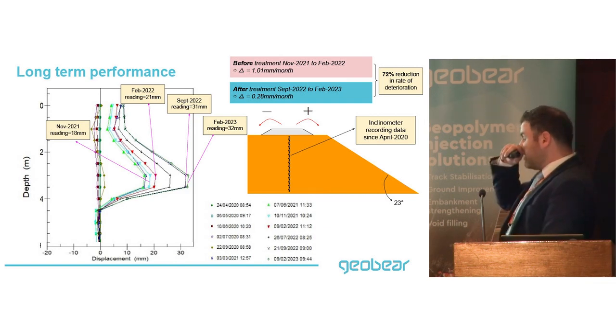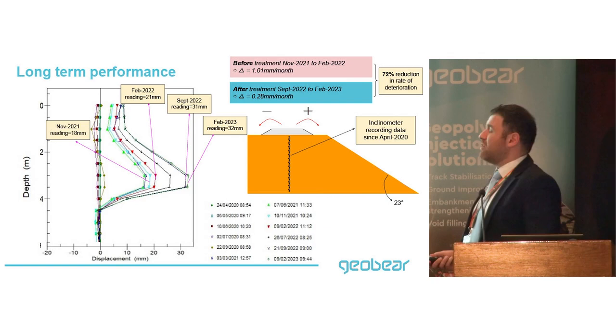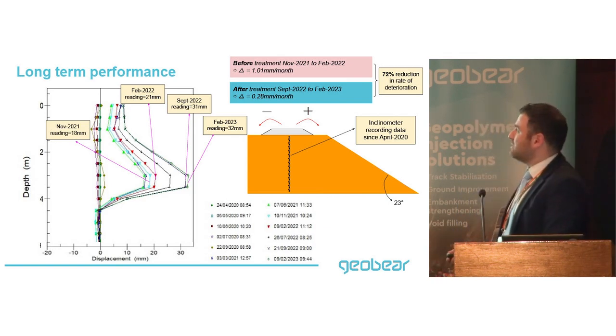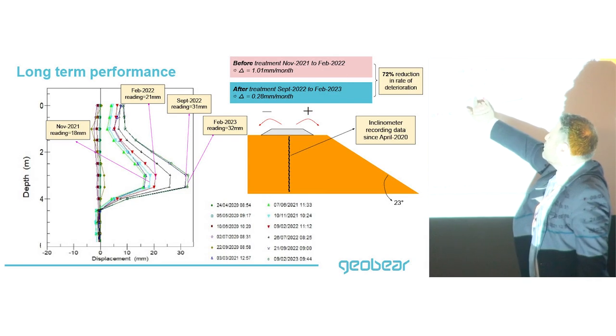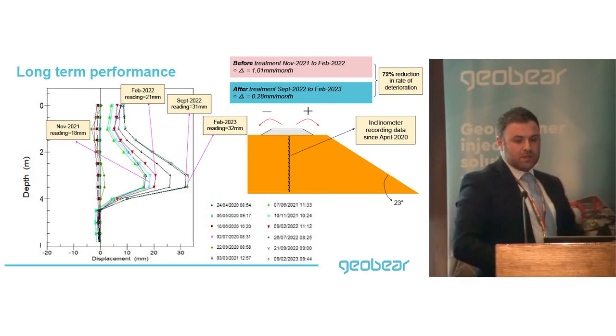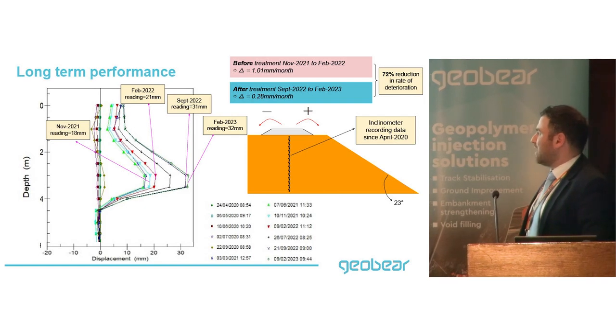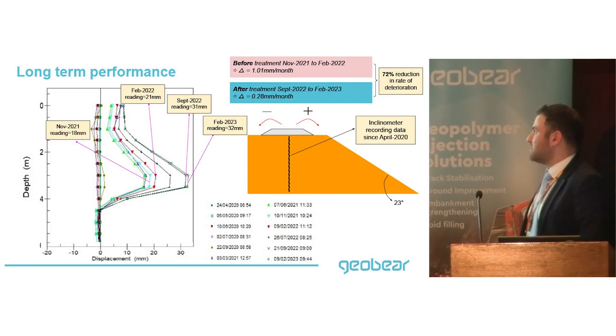That will give you a rate of deterioration of about 1 millimeter a month, roughly, if you take the delta between the two measurements and normalize them by the number of months. This is really quantified by the gap, which shows how much movement has been exhibited between those two periods in terms of how the core of the embankment has actually moved sideways towards the river.